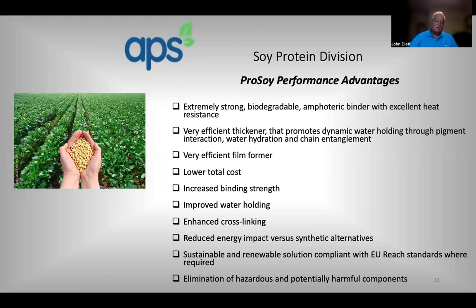So when we talk about these benefits, you say, okay, what does the customer get out of it? What's their benefit? Well, there's a couple different ways that you could go about getting this benefit. You could cut coat weight, which would save you a whole lot of money, depending on how much board you're producing. That's very hard to control. We typically say that the TiO2, because it is distributed more uniformly throughout the coating matrix, you can start pulling a little of that off. You can start pulling out, go with a lower total binder level. Those things are a lot easier to control than it would be to start cutting coat weight, although it is possible and it has been done.